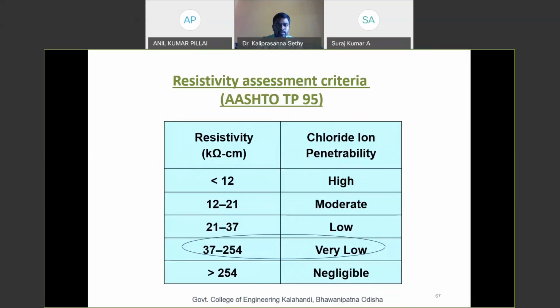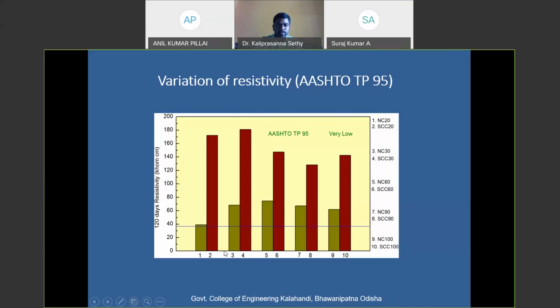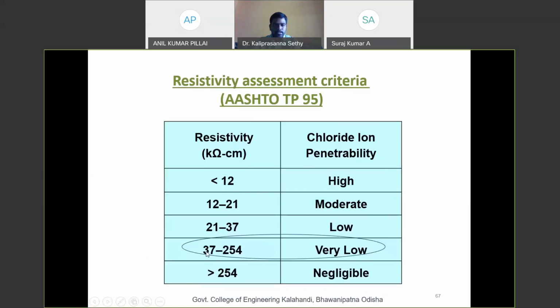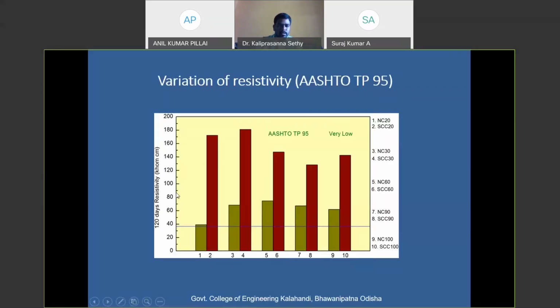As per the standard AASHTO TP 95, if the resistivity value is in the 37 to 254 range per centimeter, the concrete has very low chloride penetrability. From this bar chart you can see the range plotted, 37 to 254. All the concretes are within this range. Though it is normal and self-compacting concrete, both are showing very good resistance to chloride penetration.